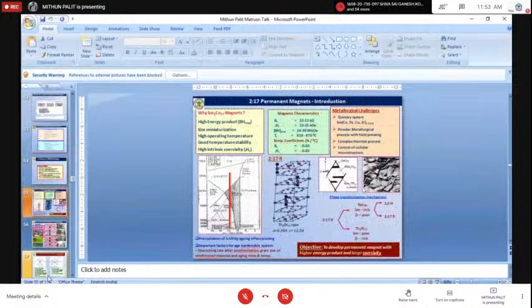So let me begin my presentation with this part of the story with the 217 type of magnet. You can see this microstructure. There are nice fine precipitates distributed in the cells in the microstructure. In this 217 type magnet, the coercivity comes from the interaction of domains with these fine precipitates, which are all SmCo5 type precipitates. They have strong anisotropy, and thereby they pin the magnetic domains very, very efficiently.